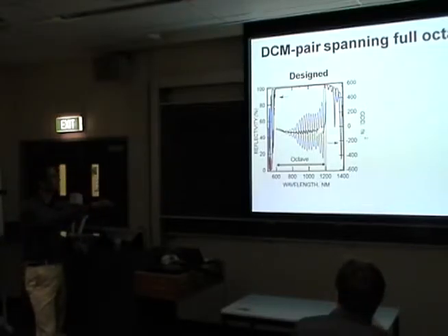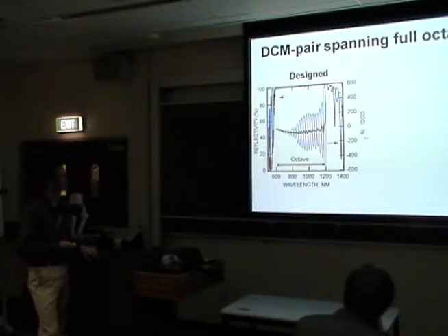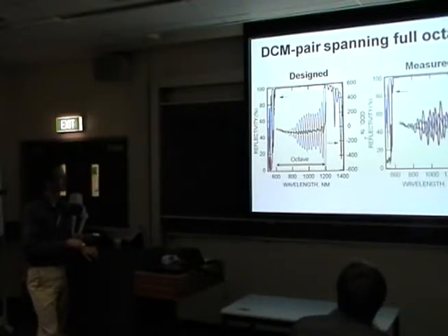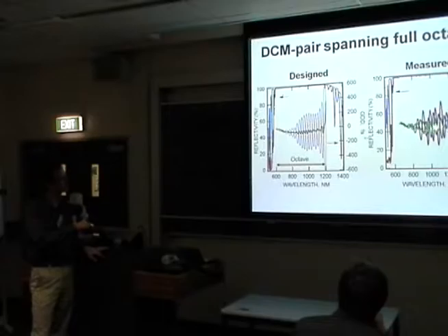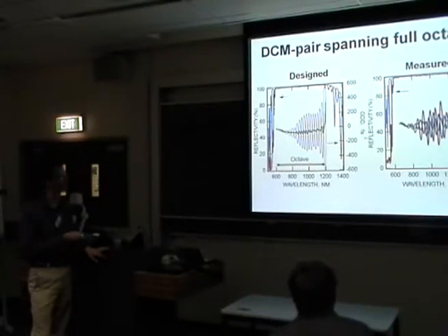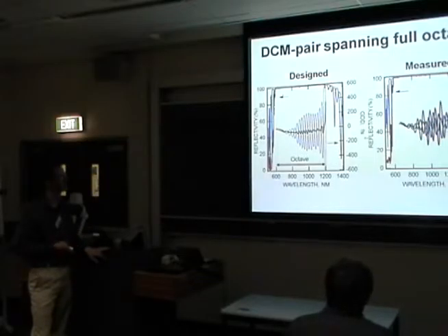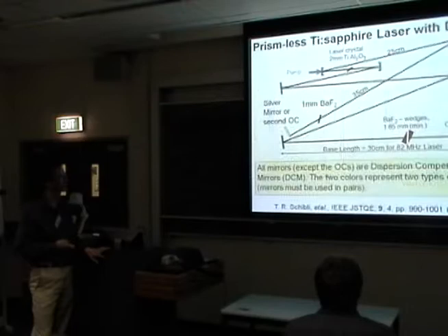After this double bounce, I end up with the green curve, and so a nice cancellation of those oscillations. In practice, since you have these 10 nanometer layers, it didn't quite work as well, but it's still significantly better than anything we have had before. And so the oscillations are still pretty small. And we actually did get a full octave of reflectivity, a little bit more.